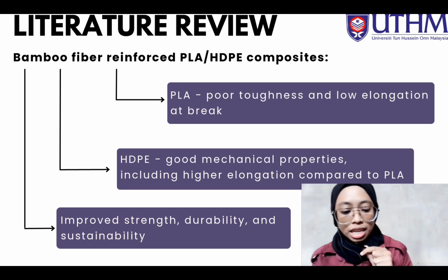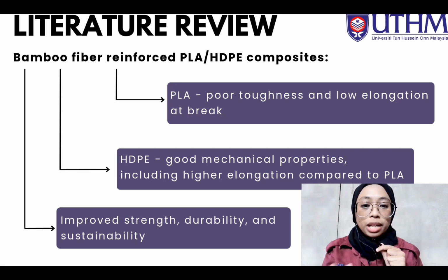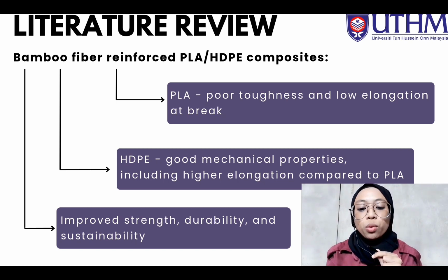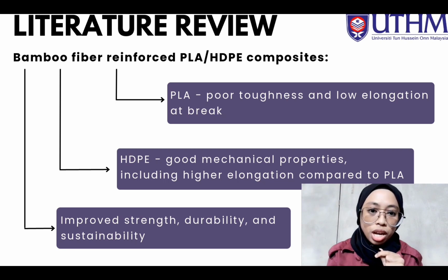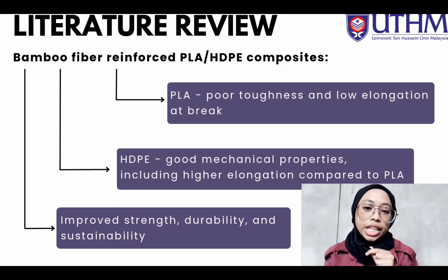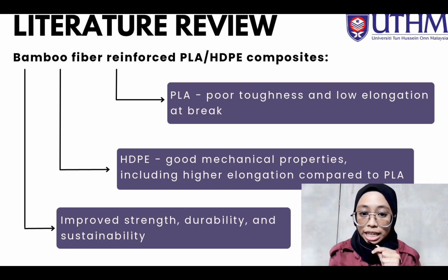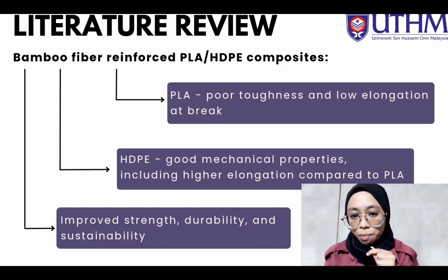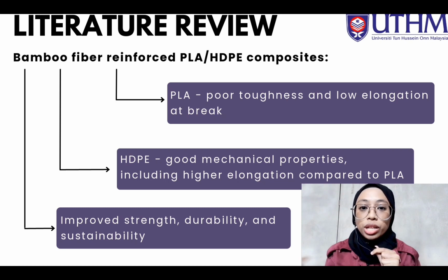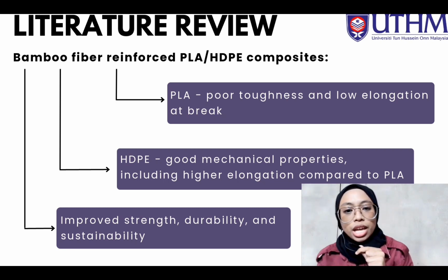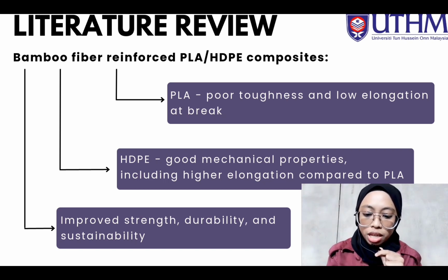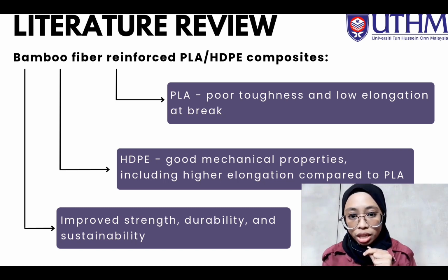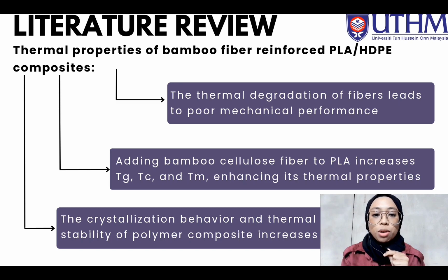Next is about bamboo fiber reinforced PLA HDPE composite. Just like I said just now, PLA has poor toughness and low elongation at break. Meanwhile, HDPE has good mechanical properties, including higher elongation compared to PLA. Bamboo fiber also has good mechanical properties, but it has poor interfacial adhesion. After we treat the bamboo fiber, it will improve the mechanical properties of bamboo fiber. And then if we mix bamboo fiber with PLA and HDPE blends, it will improve strength, durability, and sustainability of the composite.